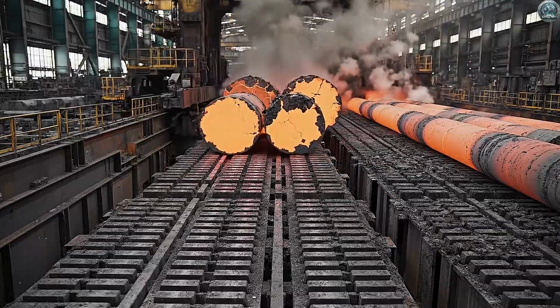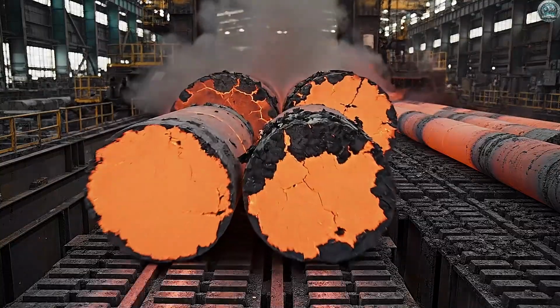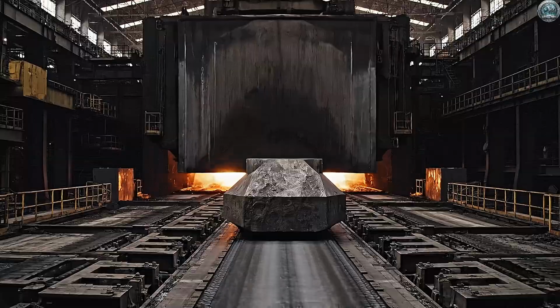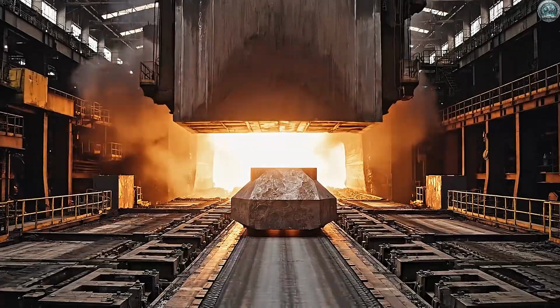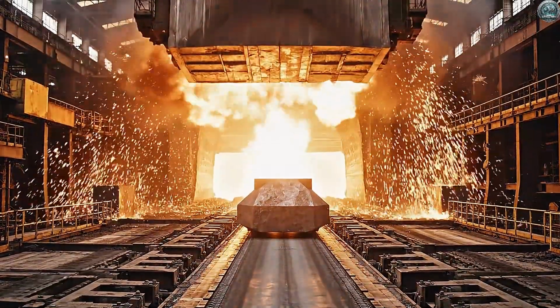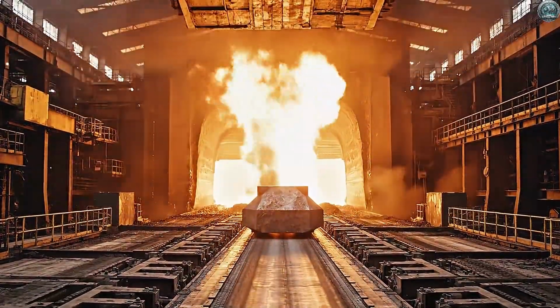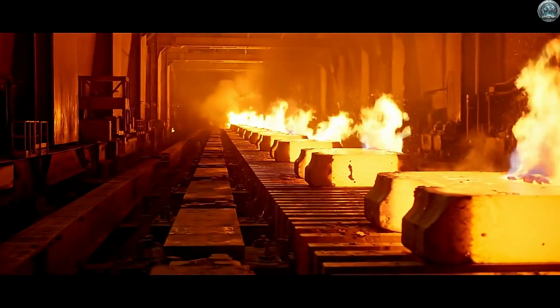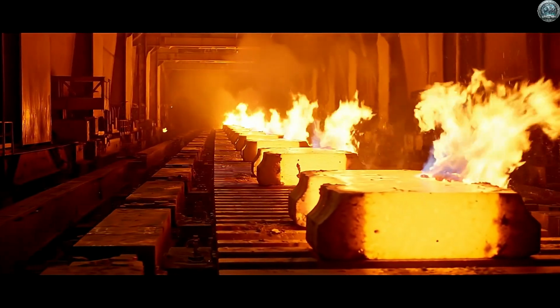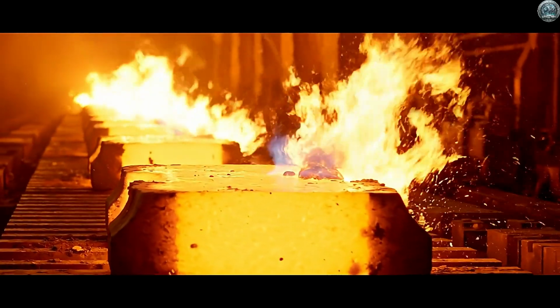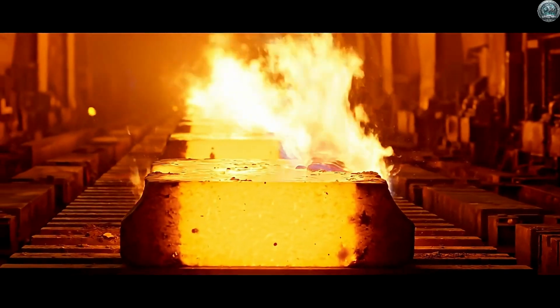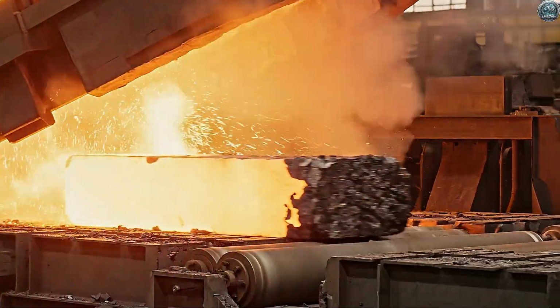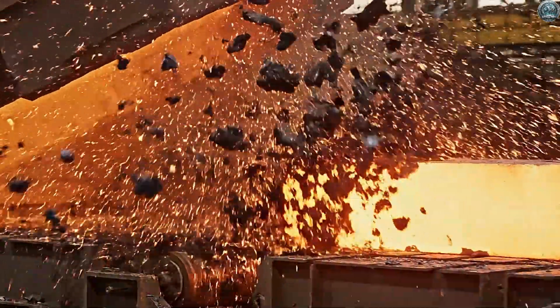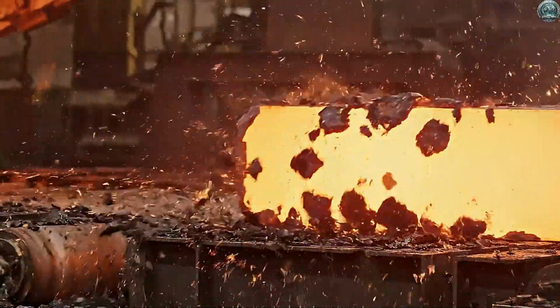They roll onto the cooling bed, a rhythmic tide of fading red steel. Weighed and tagged, the steel must be reborn in fire. It enters the reheating furnace. Soaking at 1200 degrees ensures the steel is malleable and uniform to the core. It emerges soft, glowing, and ready to roll, shedding its skin of oxidation.